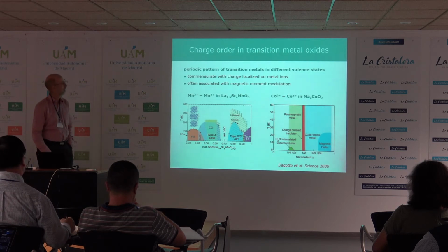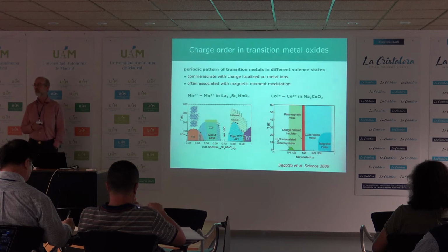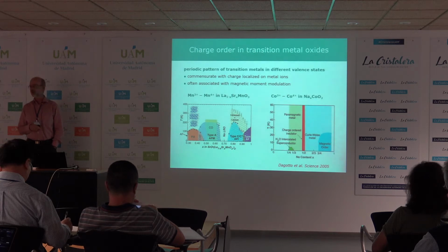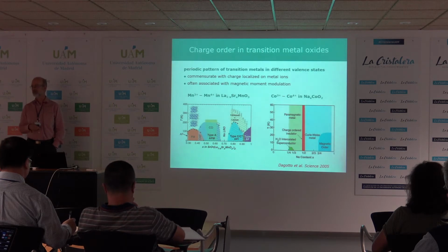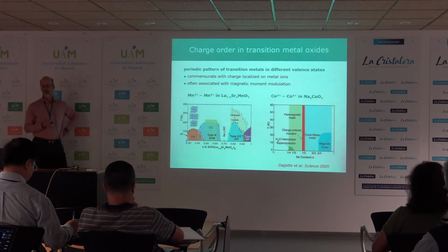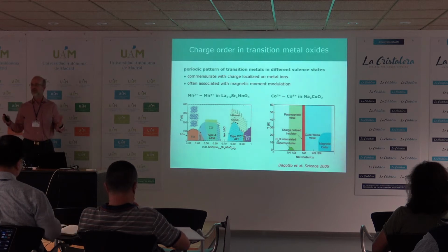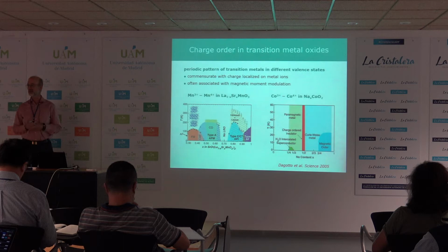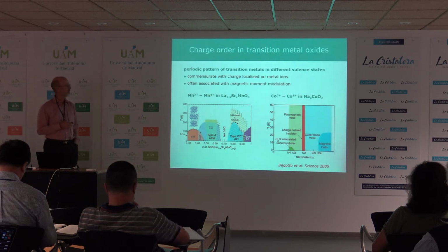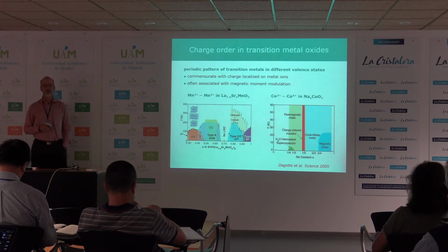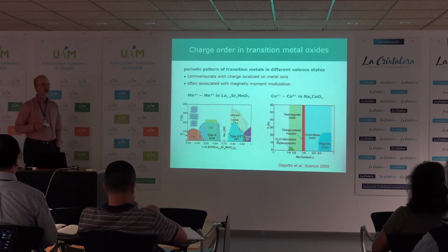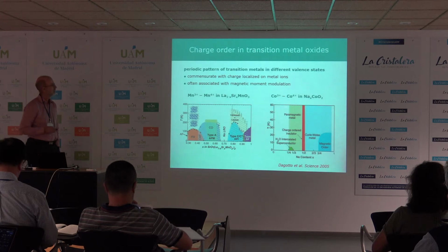And here, would you see multiple Qs because you want to have rather sharp charge density? Yes, you can have multiple harmonics. Yes, yes, that has also been seen. So you have multiple harmonics. It's not a sine wave, it's a square wave. Okay? So that's true. Often these are, however, washed out because of disorder. If you have any kind of disorder in such a state, the first thing that goes away is the harmonics. They're much more sensitive to this.